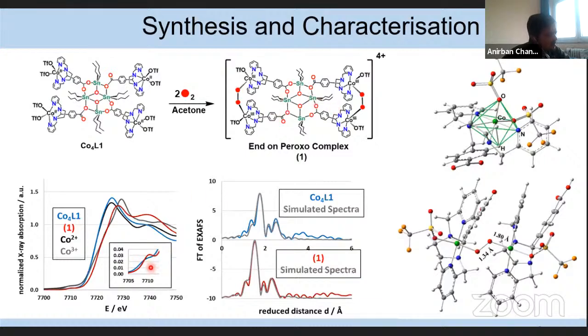more ligand field strength in the peroxo species compared to the tetranuclear complex. And in this figure, I show the experimental and the simulated spectra for the EXAFS simulation of the tetranuclear cobalt species. The blue one is the starting complex and the red one is the intermediate.